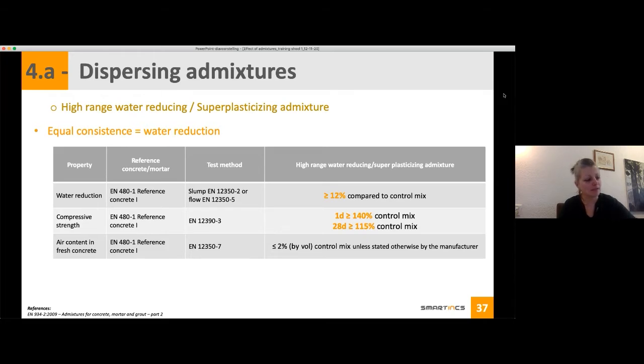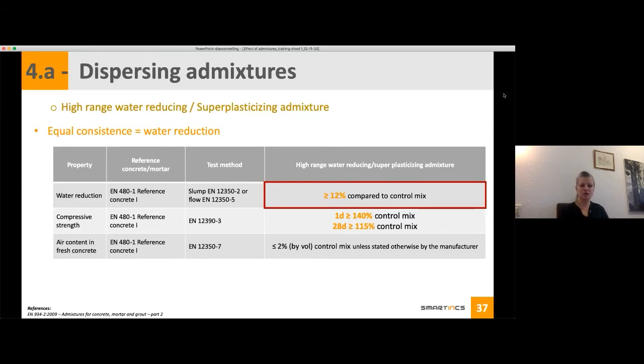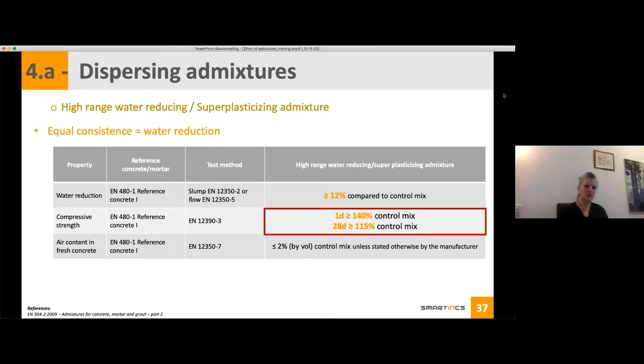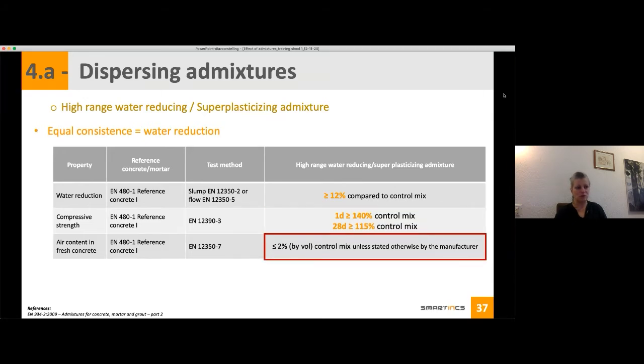So I said that we should look over a constant water to cement ratio. But then we should also look at if you have the same consistency, it means you bring some water reduction. And water reduction for a superplasticizing admixture is 12% compared to a control mix, and this is really the low end because for most of them you have 15 up to 30% of water reduction. So this is really a big reduction, so it means you can do much more with your mix design. Relating to your compressive strength, it means that after 1 day it should be more than 140% of the control mix, and at 28 days still the strength is higher than the control, even with your water reduction. And the air content should also be no more than 2% extra.